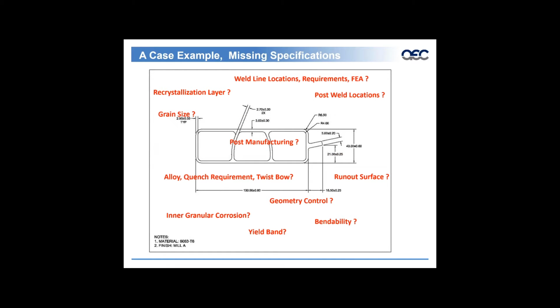So the questions that come when you see a print like that and what needs to be taken in consideration and specified for the extrusion are represented here, and the list is probably 3 times as what I've shown here. But here's some consideration. Weld line locations, and what are those requirements? And was FEA done? So for example, is it okay to have a weld line within these vertical webs? Or is there stress risers relative to the outside of the product? Or will this product be bent in such a way or crushed where the weld needs to be applied in certain areas? That needs to be understood.